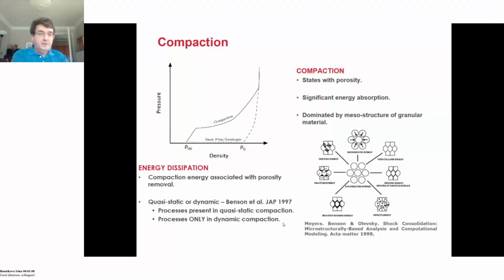And basically, here we see on the pressure density curve, you have a compaction process shown as starting at the original density, the compaction process, some kind of strength, a compaction region up to something that's close to a hot, fully dense material. Then upon release, you follow an isentrope and you go down, and there is a lot of residual compaction in the system. And so that area under that pressure density curve is a measure of the energy you have deposited into the system. Hence, the system can get quite hot.